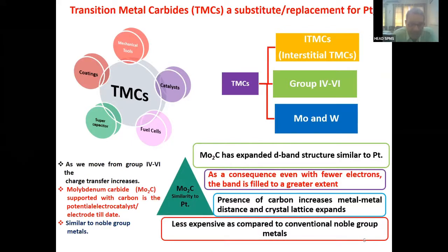Why is this so? Because molybdenum carbide has an expanded d band structure similar to that of platinum. As a consequence, even with fewer electrons, the band is filled to a greater extent, and the presence of carbon, a supporting carbon, which I will talk about later, is inbuilt there itself. The presence of carbon increases the metal to metal distance and the crystal lattice expands. This is the key feature for molybdenum carbide, and it makes for similar structural parameters to those of platinum. Another important thing is that molybdenum carbide is less expensive compared to noble metals like platinum, palladium, and other metals. So that is why it has become very, very important.